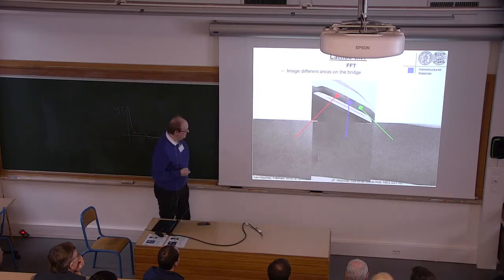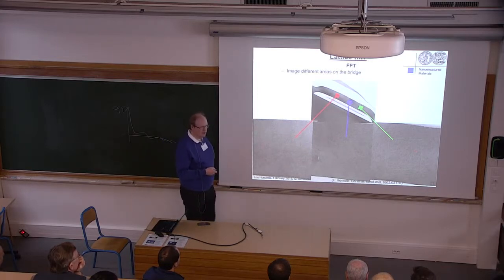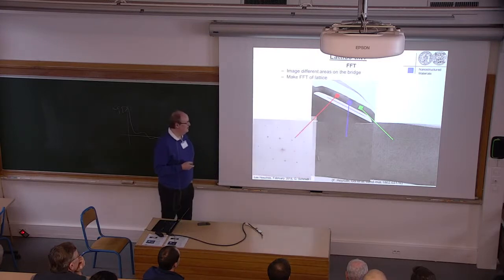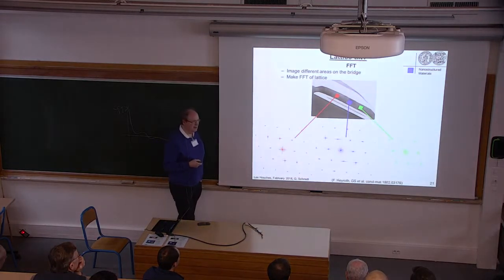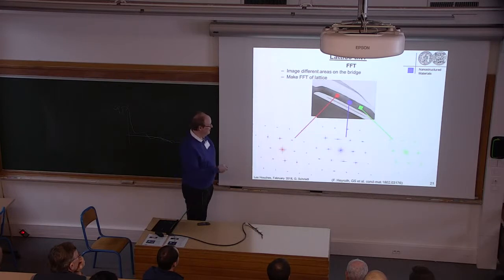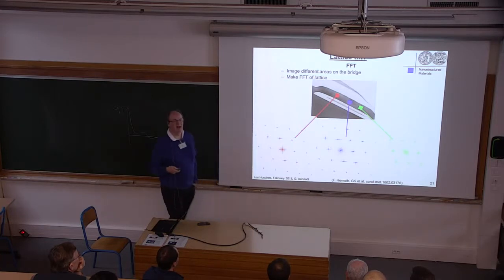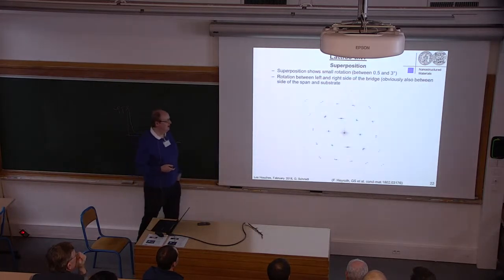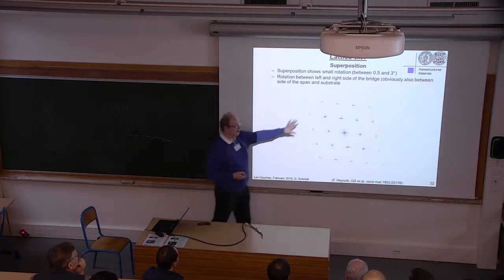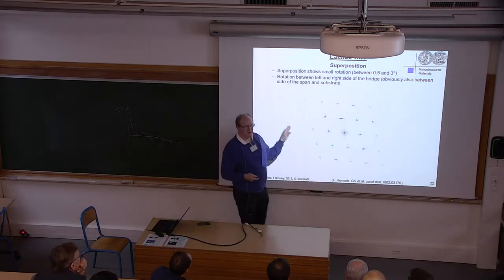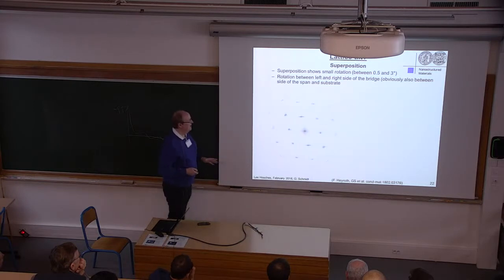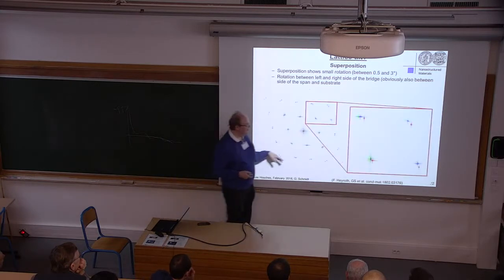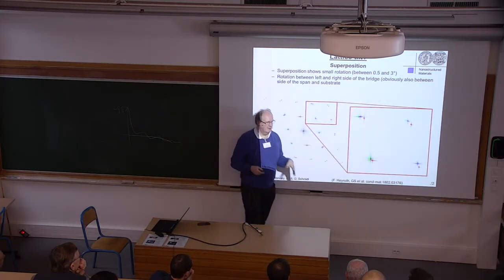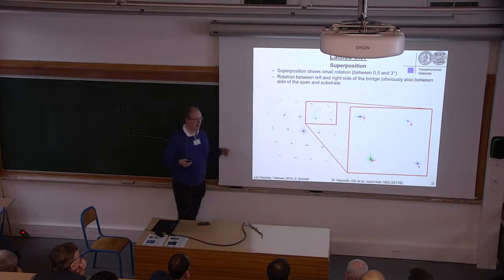You don't see the frames here, but anyway, you can see that all these areas are monocrystalline. And then what we do is we do a fast Fourier transform of the lattice in that area. So we have put it here in different colors, and in different colors you can superimpose it afterwards, and you can see that there is a very small rotation between the different parts of the bridge. And if you zoom in, you can even exactly measure what kind of tilt you have.